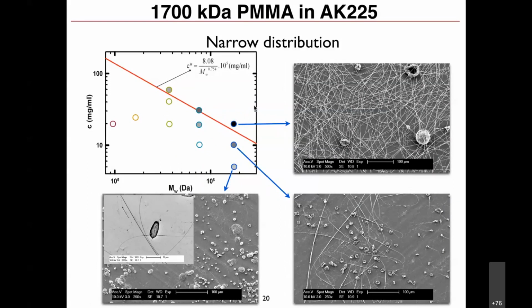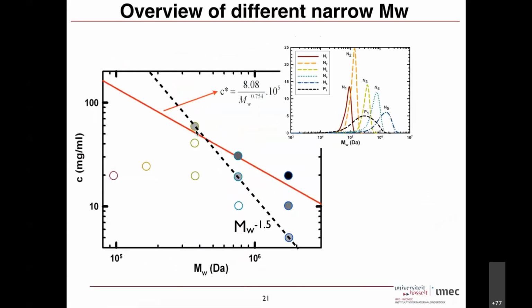So the theory says that, but when you do experiments, you see that there is also some kind of a scaling coming here. And that is what we did. So we knew that, okay, this is what the old theory says. And from experiments, we know that there should be a line here. And if you plot that line, that comes as molecular weight to the power of minus 1.5. That's how it looks. Now we need to explain why this is 1.5 and what is the explanation behind it. And for this, of course, you need to do some theory. And we also did some theory with a professor at MIT.